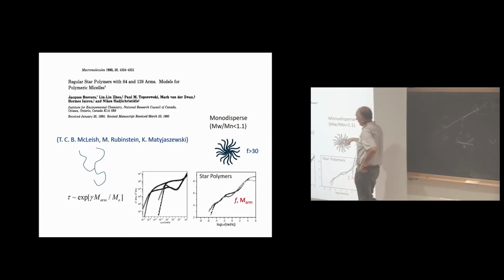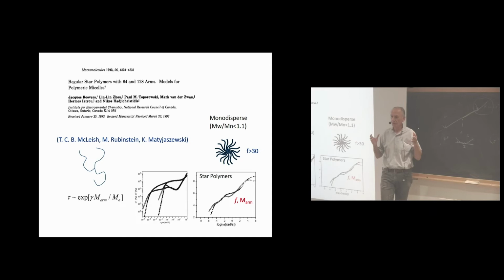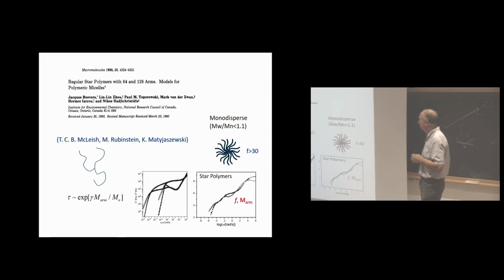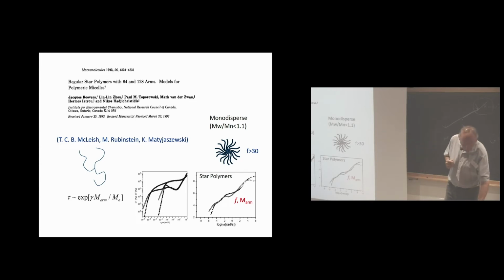Nevertheless, when you go from 3 arms to more than 30, which is this creature here, then you have this first part, which is pretty much what you saw. This is the glass here, the polymeric glass. So you have the plateau and then it drops. So this is the arm relaxation. And then you have a second mode that relates actually to the fact that this is now a colloidal object, right? And so relaxing the arm, it's not sufficient for the motion of the center of mass. You need actually this kind of gauge escape, which relates a little bit to what you mentioned, and we'll see this in a minute. Okay, so this is now the stars.